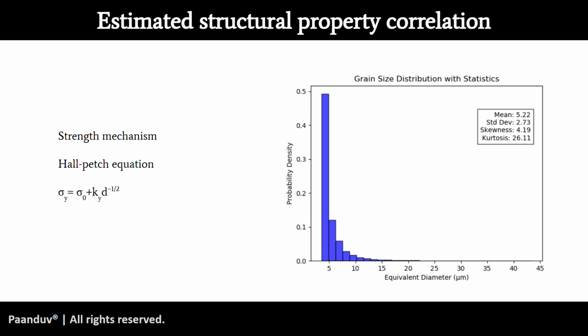You can estimate the structural property using many empirical formulae, or you can do other sorts of analysis. That is in the hands of the material scientists or the mechanical engineers, how you really want to use this microstructure data. But in the past, this microstructure data has been used with a strengthening mechanism, the Hall-Petch equation, to predict the yield stress of your build part. And in order to do that, the AM PravaH software not only gives you images, but it also takes the entire 3D grain information and gives you the mean, the standard deviation, and higher moments for that data, so that you can use this mean grain size in the Hall-Petch equation or other equations of your interest and predict the yield stress, hardness, corrosion resistance, and other mechanical properties of a build part.